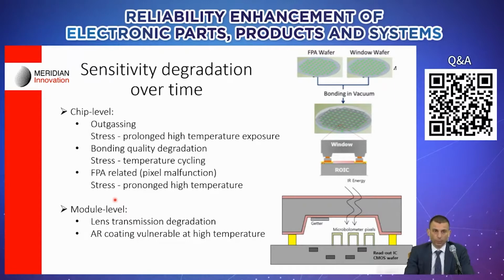Basically, there is some sensitive element that is realized in our case in one wafer together with the readout circuit, and then there is a so-called cap wafer, or here it is called window wafer as well, that is put on top, and the two wafers are bonded together. And so the strength of that bond is in some sense a point of great concern. Every manufacturer has their own proprietary process and procedures to establish the strength of the bond. But if that bond deteriorates, you get sudden loss of vacuum, and the performance of the sensor goes out the door immediately. Basically, you cannot sense heat anymore.